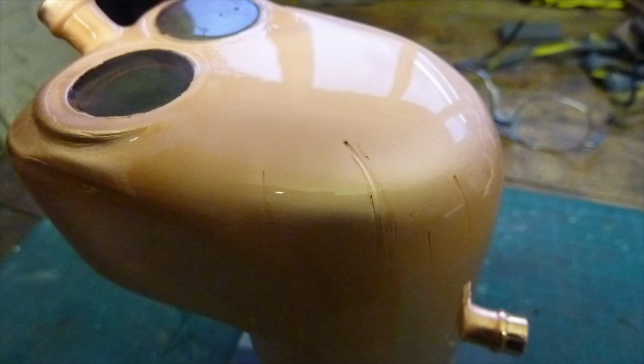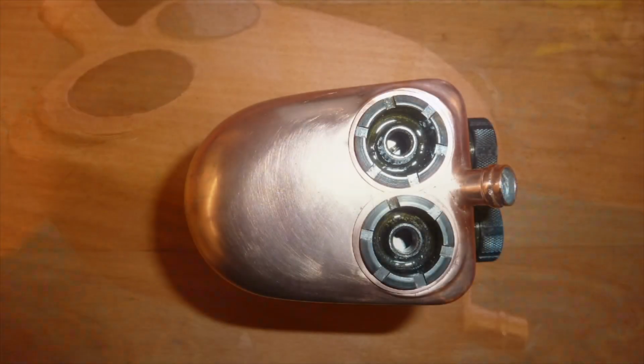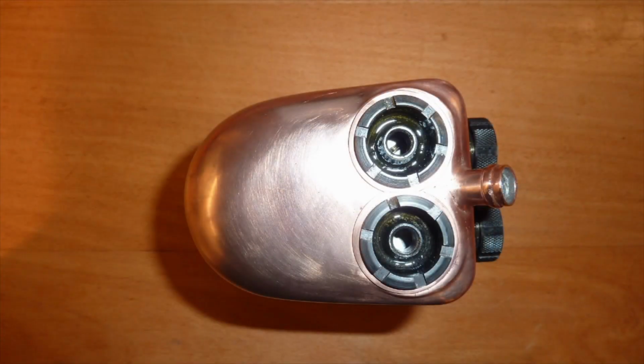I simply don't know. These pictures show some mystery defects, small scars and pits that simply appeared, perhaps caused by bits of muck settling on the surface or the dead flies that I found, and quickly getting trapped by copper being deposited around them. So I did sandpaper them out after about 24 hours and then carried on with a further day. Then a final sanding, followed by polishing, resulted in a clean finish that seemed acceptable.